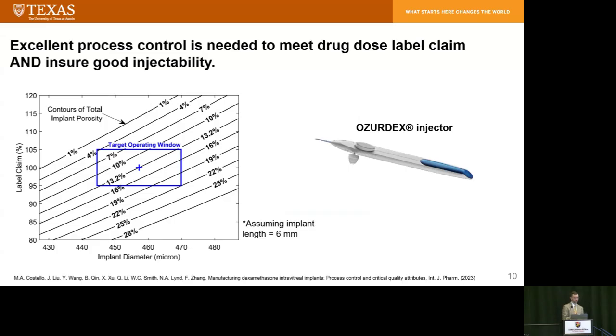And so in order to have the target dose of, I think, 700 micrograms of dexamethasone, the implant diameter has to be very well controlled, and the implant porosity. So this target operating window shows you that you have a very narrow range of acceptable diameters and a very narrow range of acceptable porosities that you need to get that target dose.